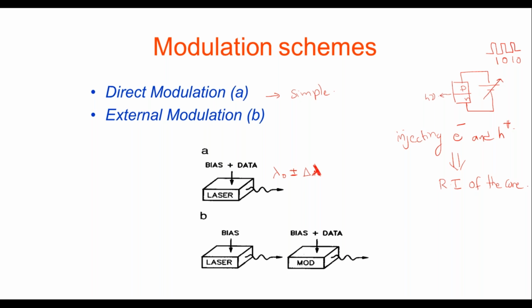So this drift in the laser wavelength because of the injected carrier density is what is called wavelength chirping, or, more commonly, frequency chirping. This phenomenon happens when you try to turn on and turn off the laser diode at very high speeds, that means exceeding something like 10 gigabits per second. If you are turning the laser diode off and on at speeds exceeding 10 gigabits per second, you would see a significant change in the refractive index, and accordingly a significant change in the emission wavelength of the laser diode, and this phenomenon is called frequency chirping.